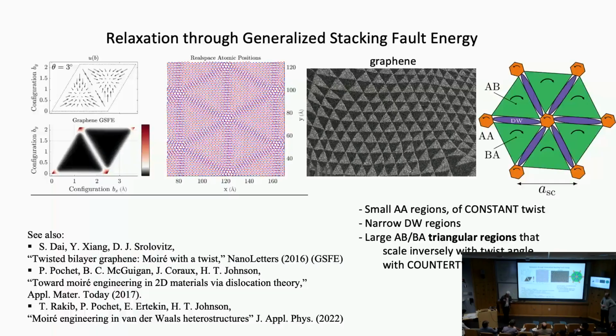That's why you can have antiferromagnetic ordering or something equivalent, because you don't hop directly from one triangular site to another triangular site. You hop through the domain wall, through the Kagome lattice. And it's the coupling of those two that would produce something interesting. Now, we're working toward that goal, to have a model with the absolute minimum amount of information from ab initio that can capture these things, but we don't have a full answer yet. There are other efforts in the literature to do that.